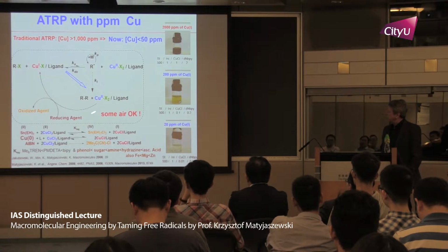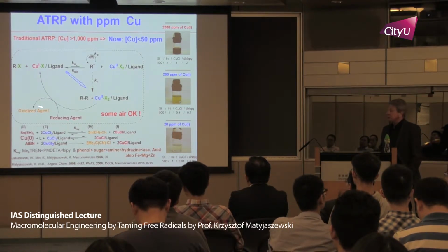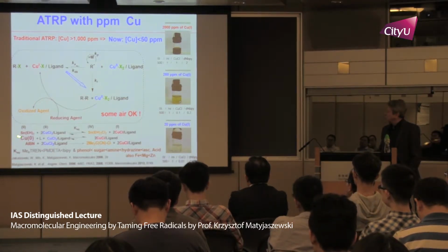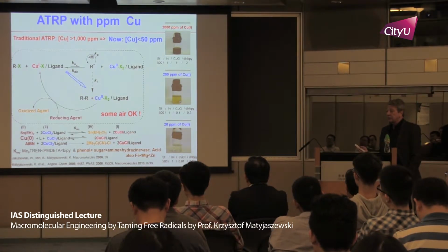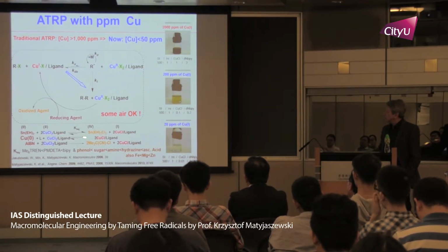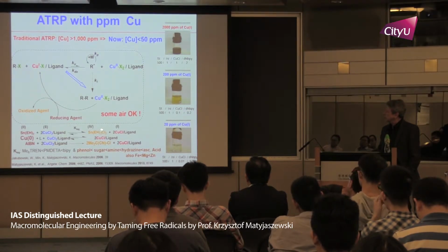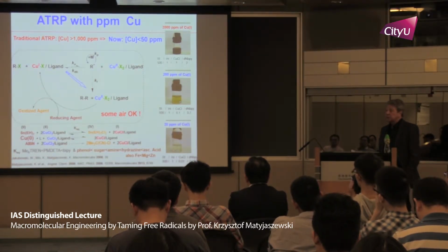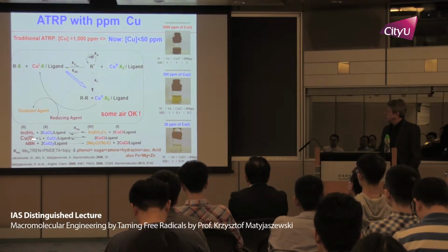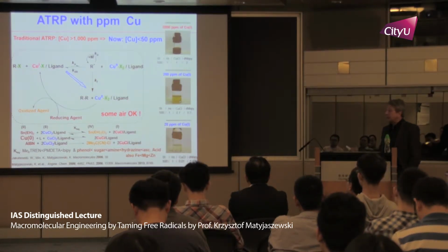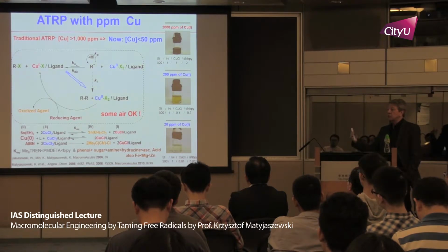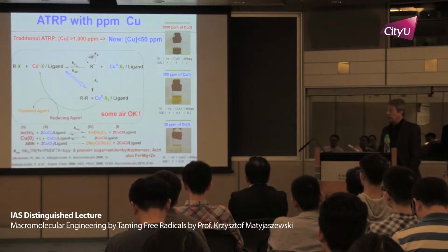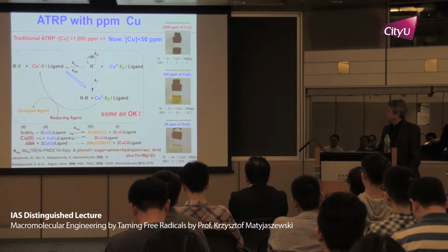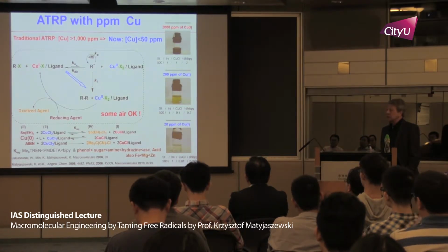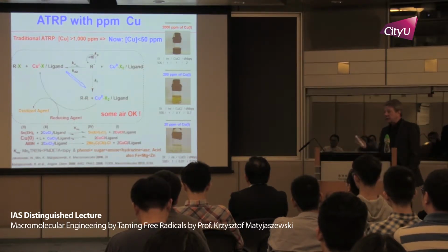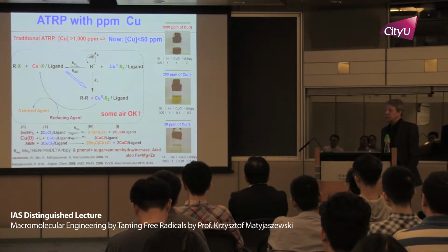However, every act of regeneration will form an oxidized agent. So for example, tin 2 octoate is very benign, but after oxidation, you form a much stronger Lewis acid, a tin 4 compound, which is toxic. If you start from AIBN, you produce more alkyl halide, you generate new chains, and you cannot make a clean polymer. So can I avoid formation of this oxidized agent completely? How can I run this reaction without these byproducts?